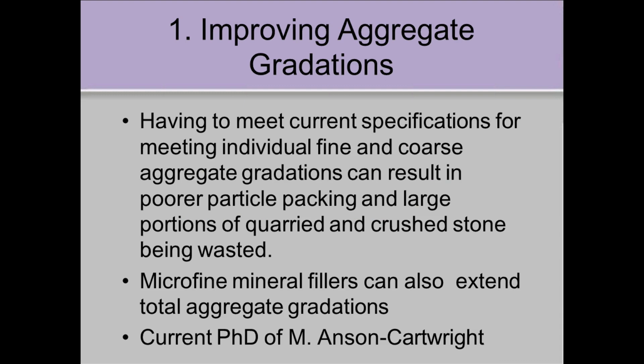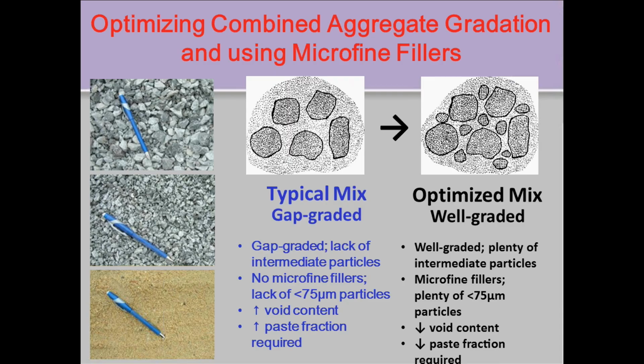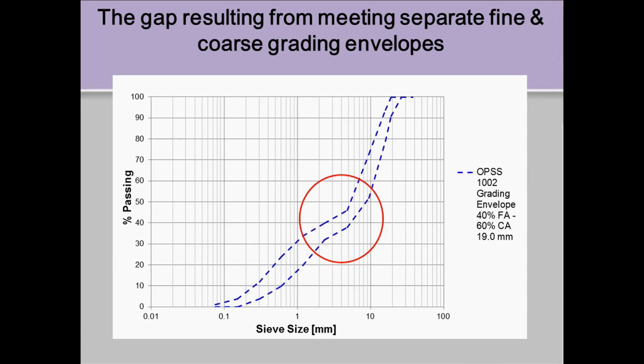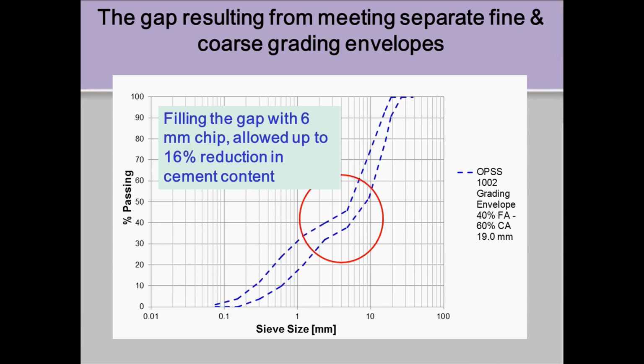We're doing work on that for the industry. And just to show that, if you take an intermediate size aggregate, that could fill in the spaces. This is typically done more so in Europe where they have multiple bin silos. This hasn't been the North American tradition. If you look at a grading curve, if you just took sand and stone, you end up with that little gap in the middle. And it doesn't look like much, but it causes you to have issues.